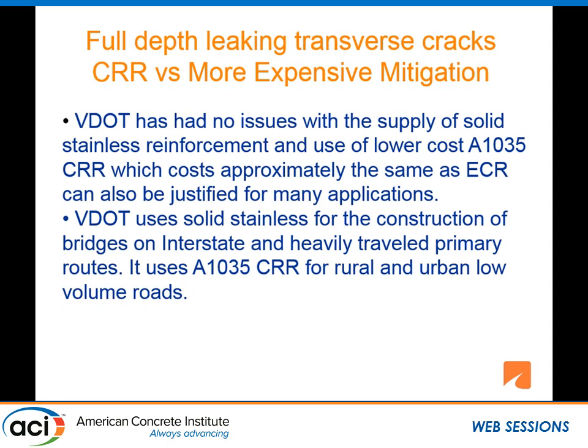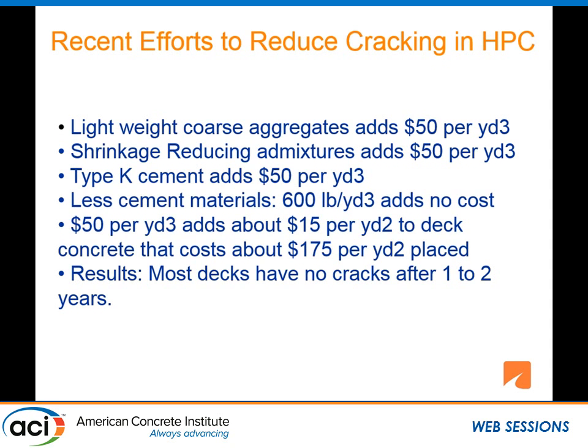Corrosion-resistant rebar versus more expensive methods. We've had no issues with the supply of stainless steel or other corrosion-resistant rebar. VDOT uses solid stainless for bridges on interstates and heavily traveled primary routes. It uses A1035 for rural and urban low volume roads. Recent efforts to reduce cracking include use of lightweight aggregates, shrinkage-reducing admixtures, type K cement, and less cement. All of these have shown promise in reducing the cracking index.